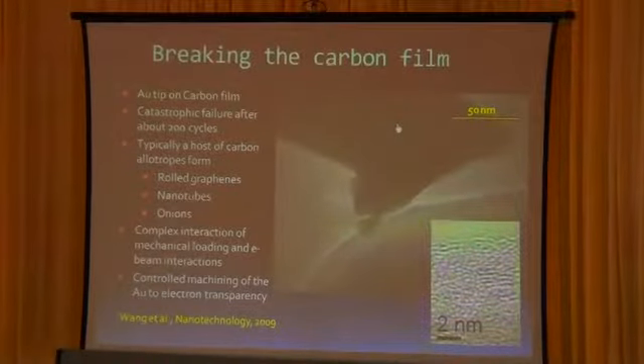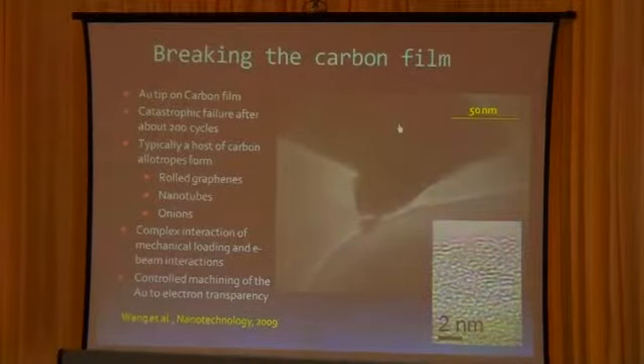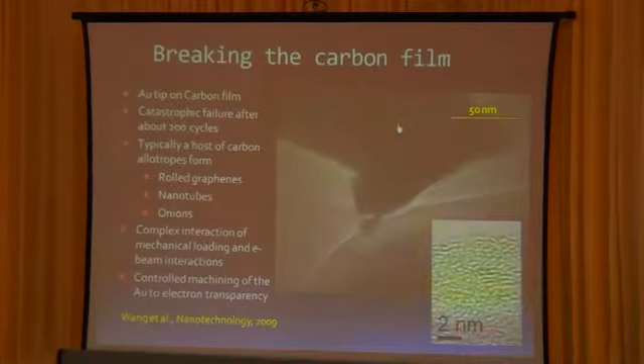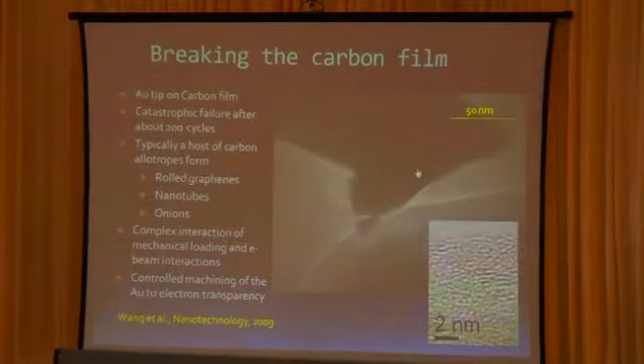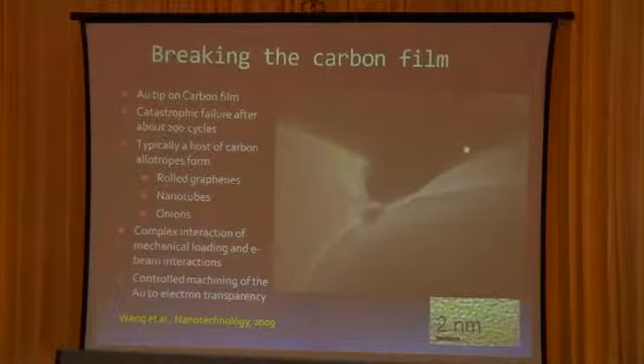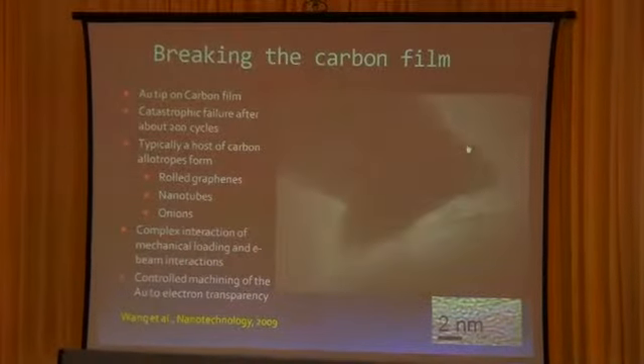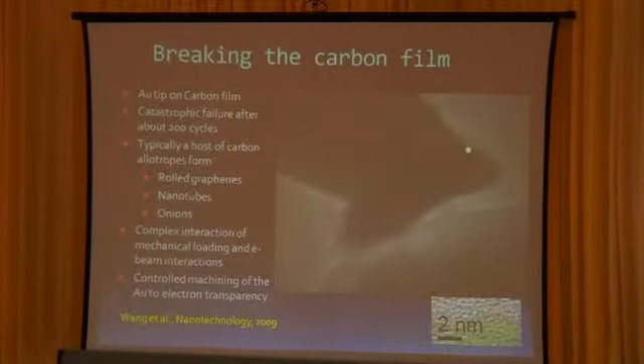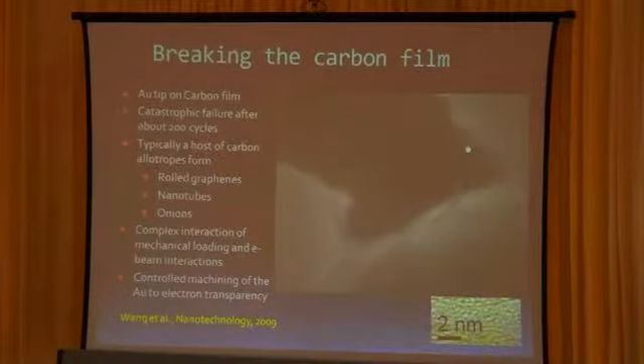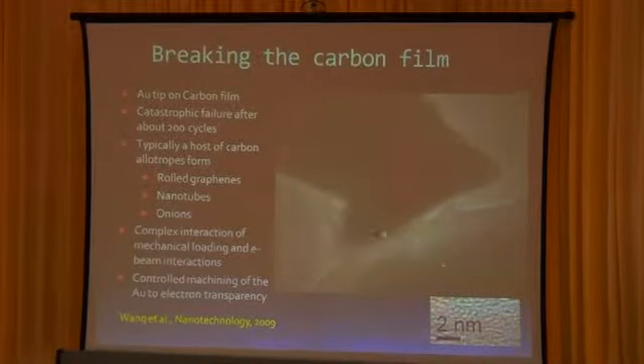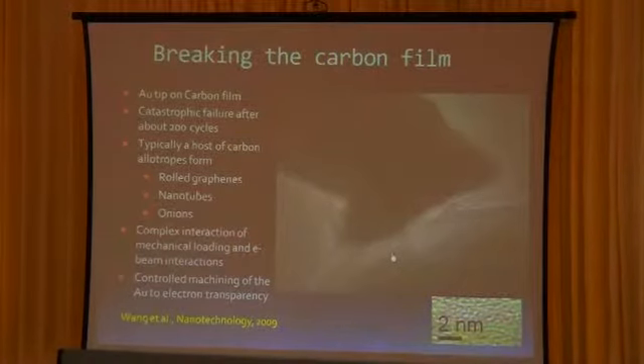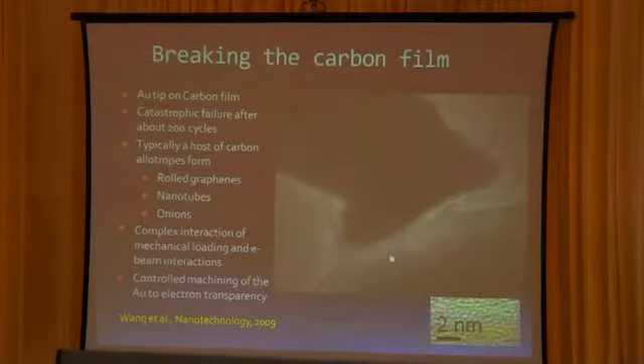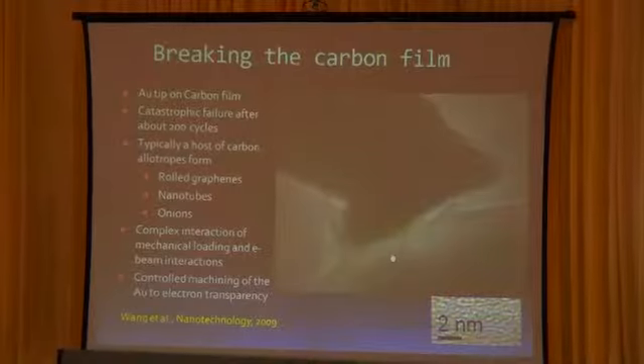Right. So in spite of that, if the stiffness is low, so what? We can repeatedly do fatigue loading. We can rub again and again and again, and see what happens. This is an already deformed carbon tip, a sharp tip, rubbing against a carbon deposit on gold. This is gold, this is gold, and in between a carbon film is there. By rubbing again and again, after about 200 cycles, the carbon has suddenly, catastrophically deformed.